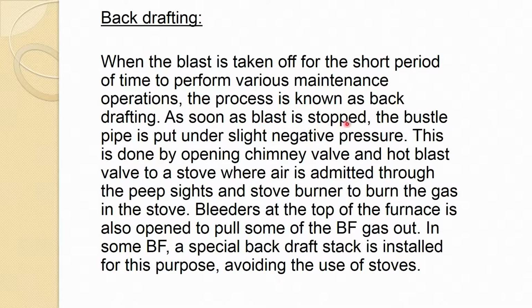As soon as blast is stopped, the bustle pipe is put under slight negative pressure. This is done by opening the chimney valve and hot blast valve to a stove, where air is admitted through the peep sights and stove burners to burn the gas in the stove. Bleeders at the top of the furnace are also opened to pull some of the blast furnace gas out. In some blast furnaces, a special backdraft stack is installed for this purpose, avoiding the use of stoves.